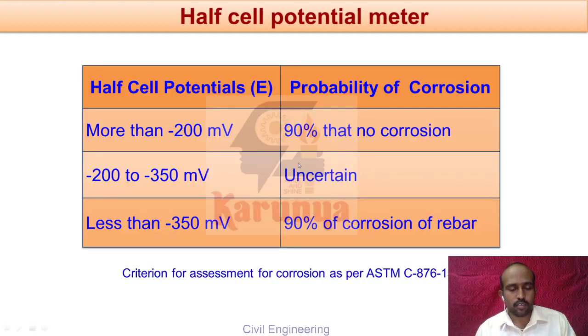So this table shows the values and the possibility or probability of corrosion. If the potential meter value is more than negative 200 millivolts, the possibility of corrosion is very low, 90% no corrosion. If it is between negative 200 and negative 350, the corrosion is uncertain, may or may not. If it is less than negative 350 millivolts, the possibility of corrosion is high, 90%. The structure may be corroded.